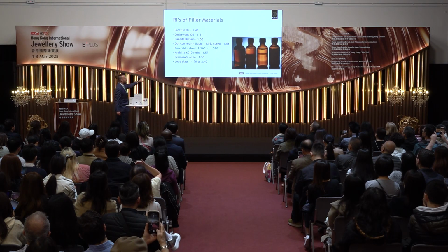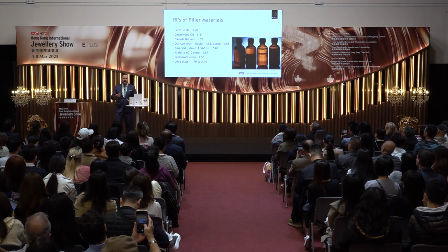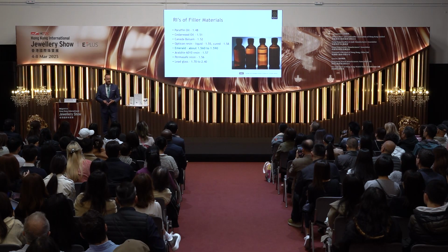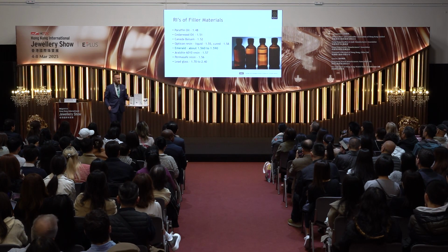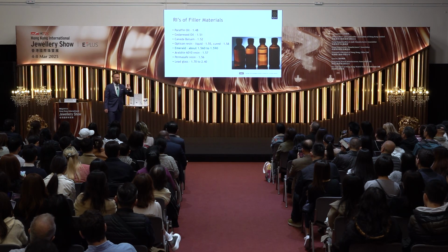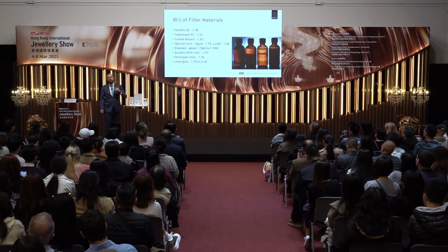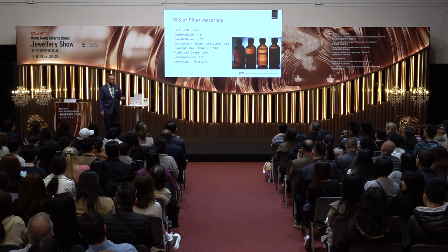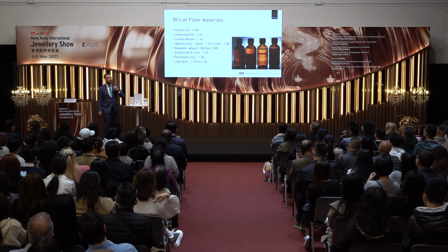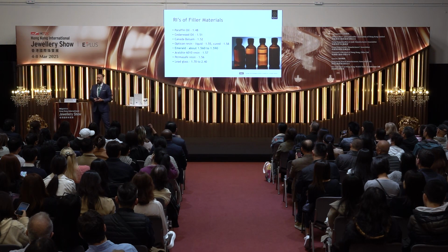But also I want to add at the bottom that people ask, why can't you put glass in there? Because glass would be a lot more stable, a lot harder, a lot more difficult to remove, a lot more chemically resistant, heat resistant than oils. Why can't you put glass in there? And I think here you can see, because the difference in optical properties between a glass and an emerald is way too big. So glass would do a terrible job at hiding a fracture in an emerald. Glass would do a terrific job at hiding a fracture in a corundum, but we're going to talk about that in 10 minutes.